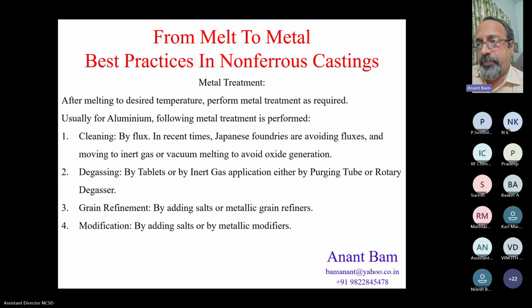What is the purpose of treatment? Cleaning basically removes oxides and reduces oxide inclusions. Degassing reduces or eliminates hydrogen, the only soluble gas in aluminum, which is the cause of pinhole porosity. Grain refinement makes the grains smaller. It leads to improvement in ultimate tensile strength, and it helps in reducing shrinkage porosity. Modification of silicon leads to better elongation, and also it helps in giving quick response to heat treatment.